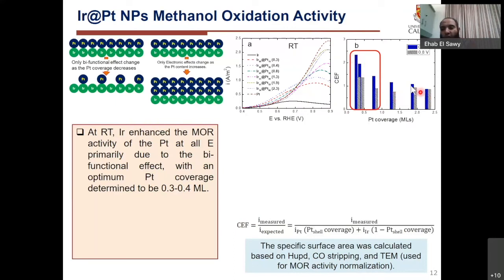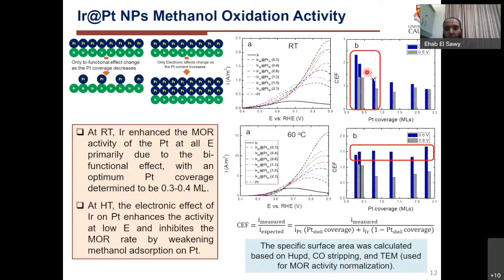However, once the coverage increases, the catalytic enhancement factor drops. That happens at both low potential, where carbon monoxide removal is the rate determining step, and at high potential, where methanol dehydrogenation is the rate determining step. We also tested at high temperature. The issue with high temperature is that the iridium regeneration of OH groups is sluggish, so the bifunctional effect almost has no effect. The enhancement factor is almost constant, which means it is related to the weak electronic effect of iridium on platinum.